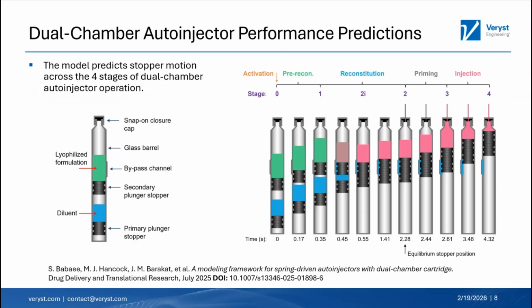The dual chamber cartridge we modeled is shown here. A spring connects to the primary stopper. The spring actually isn't shown, but it would be coming in from the bottom. Diluent and freeze-dried drug product are kept in sealed chambers, and they're separated by a secondary stopper. The model predicts stopper motion across 4 stages of dual chamber autoinjector operation, and those are reconstitution, priming, and injection. Once the secondary stopper moves past a bypass channel, air and diluent can pass into the drug chamber. And this starts the reconstitution process.